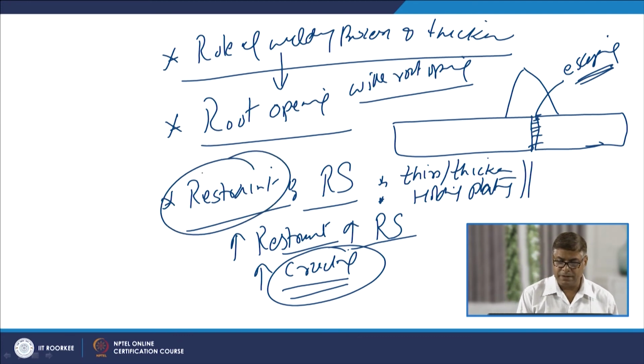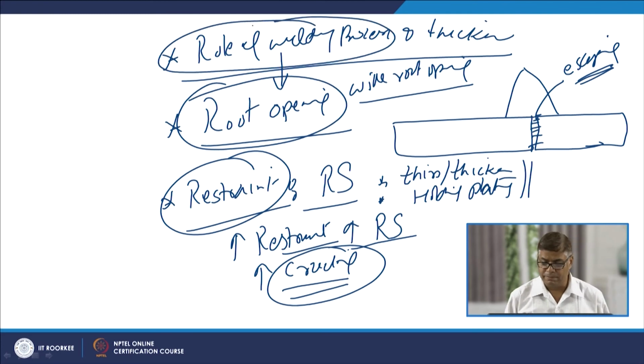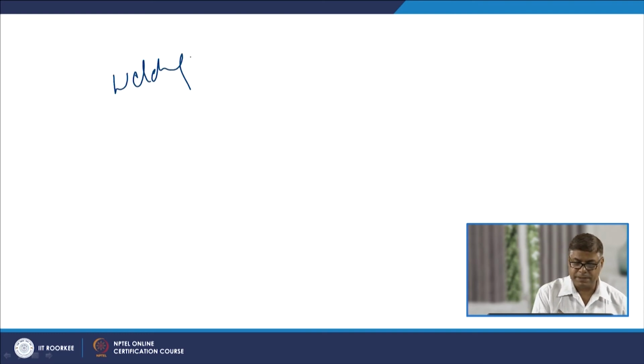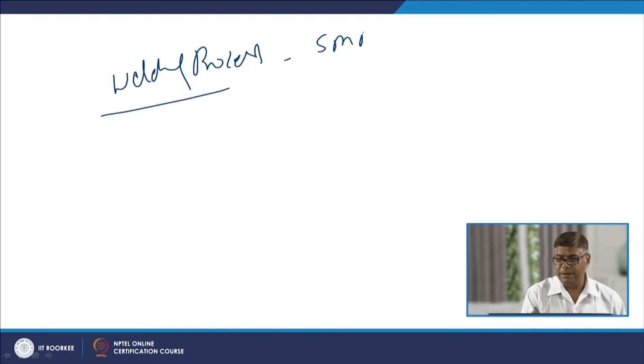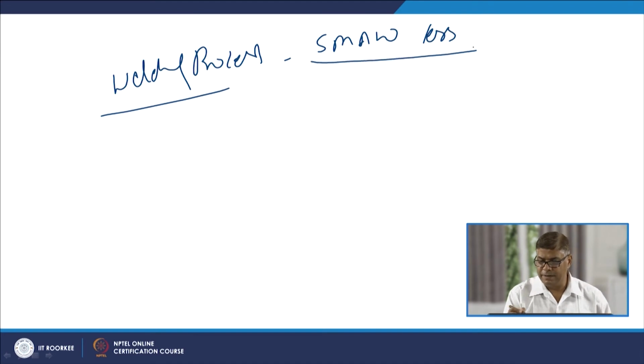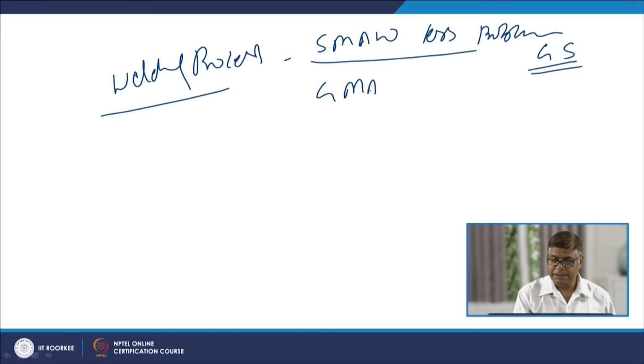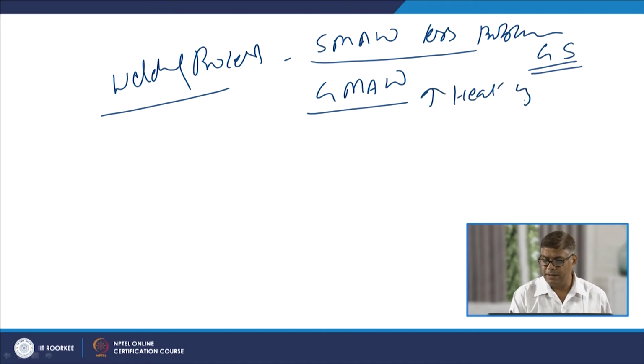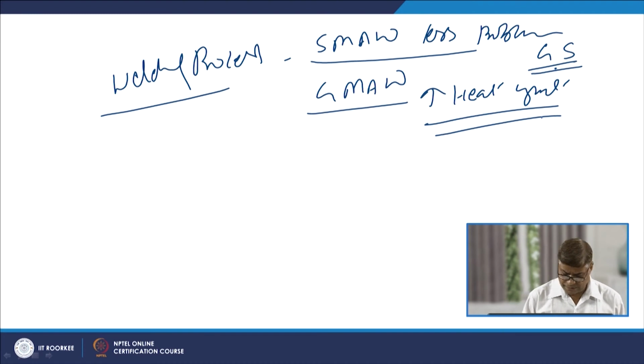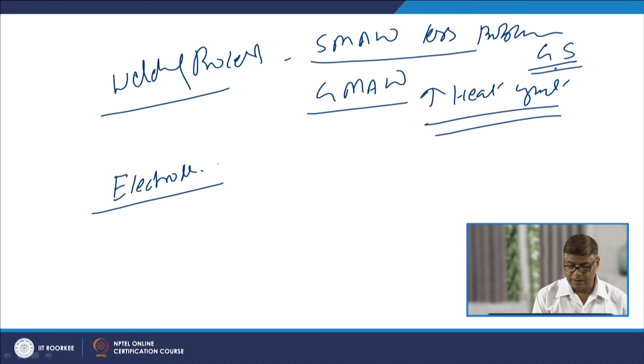So, reducing the restraint, increasing the opening, selecting the welding processes favorably, and reducing the thickness of the galvanized sheets, all these will favor the weldability and reduce the problems associated with the welding. As far as the welding process is concerned, as we have seen, the SMAW process leads to better weldability and fewer problems associated with galvanized steel welding as compared to the GMAW process. So, basically the higher heat input favors the weldability of the galvanized steel.